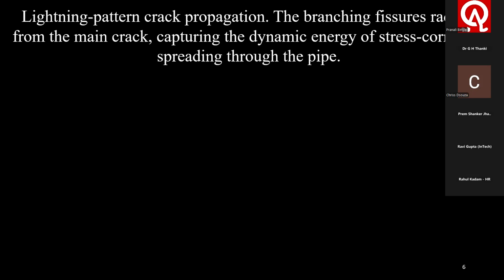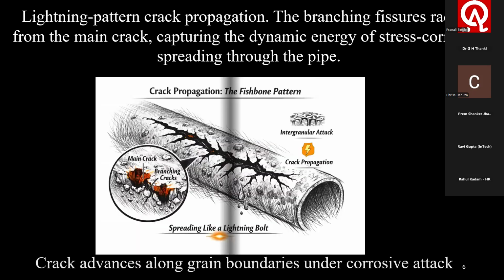Lightning pattern crack propagation. The branching fissures radiate from the main crack, capturing the dynamic energy of stress corrosion spreading through the pipe. These are step-by-step pictures showing you how dangerous this corrosion can become in our oil and gas industries. Crack propagation, the fishbone pattern. Left-hand side shows the main crack, branching cracks, and spreading like a lightning bolt.